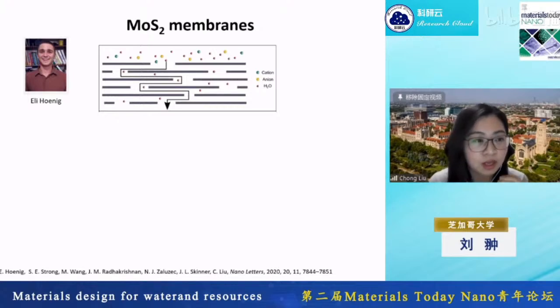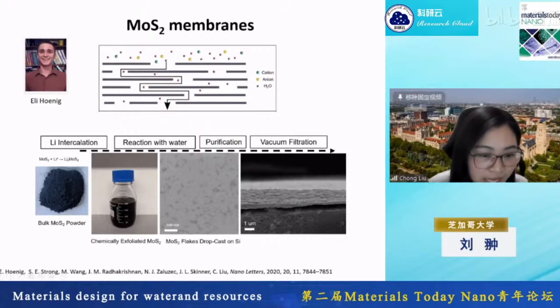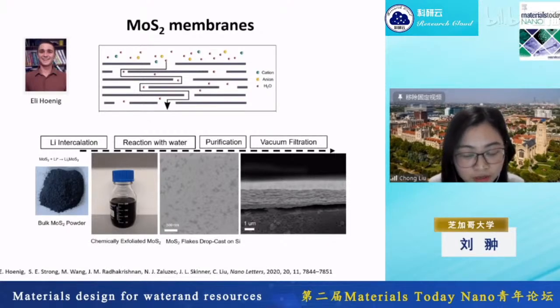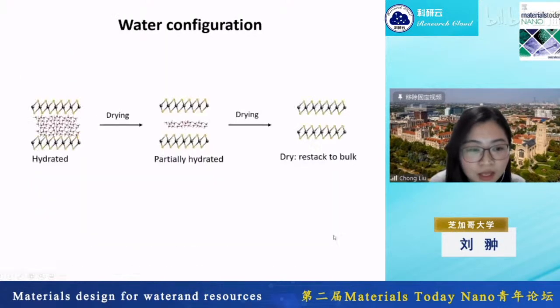The membrane we picked uses hundreds or thousands of these 2D channels, laminated together and assembled into a macroscopic membrane. In this case, you start with the bulk form of molysulfide and exfoliate it into single individual layers. You restack them into macroscopic films, and that's the membrane. Because of the nature of this solution process, the membrane is wet when processed, and the molysulfide layers have a lot of water in between them when they are first made.